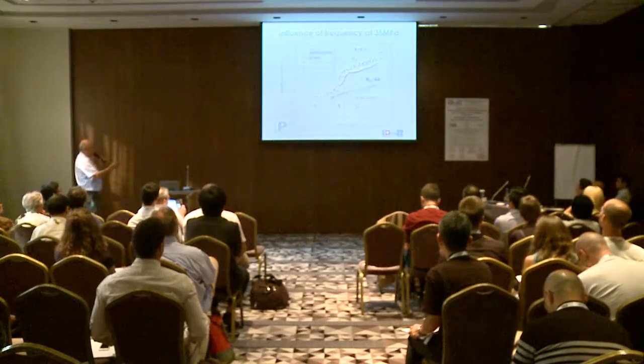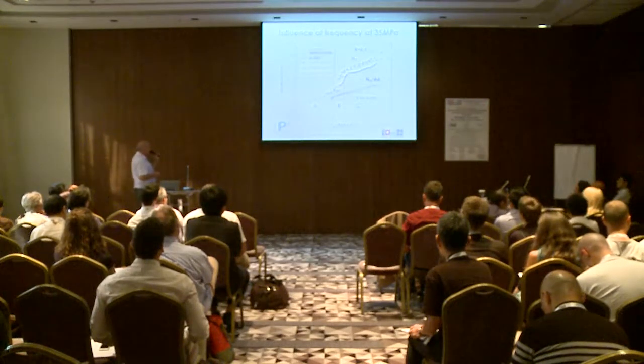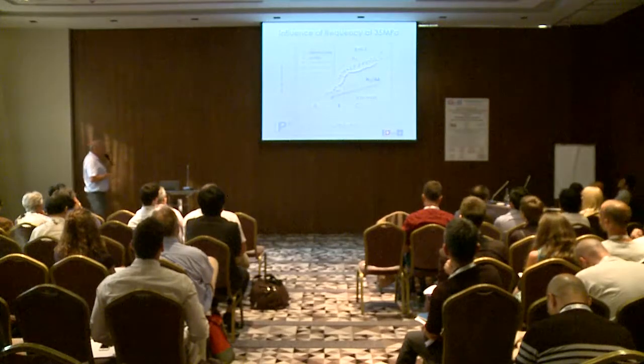Let me move now to the fatigue crack growth results. Here, for the sake of clarity, I will only present the results obtained at a hydrogen pressure of 35 megapascals with different loading frequencies. First, here you have the fatigue crack growth response of the material in vacuum. This curve is obtained under high pressure of nitrogen using the same test rig. And here, the fatigue crack growth rates measured in air. The red points correspond to the fatigue crack growth data obtained under high pressure of hydrogen.